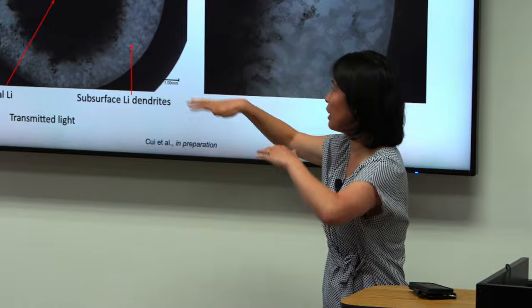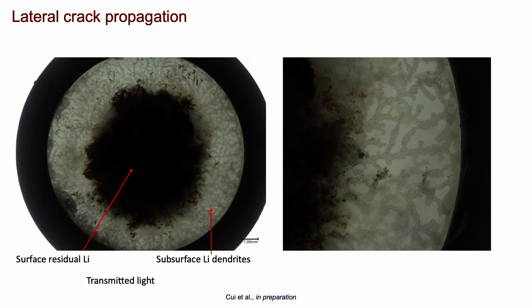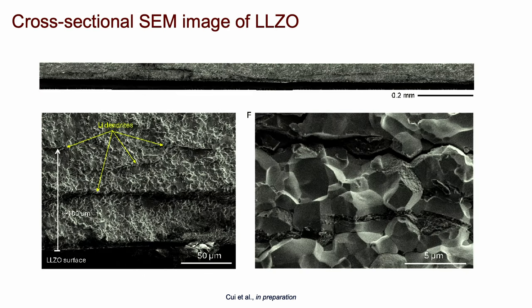So this is a picture of the LLZO after, I think, about 500 cycles of charging. What we see is this big black mass in the middle, and even at the sides, we see these tendrils. If we zoom in, we see something that looks like dendritic structures, these branch-like structures going to the outer wall. What we think is happening here is that at each charge cycle, the lithium is progressively moving in and out, and some residual lithium is left to leave these optical features.